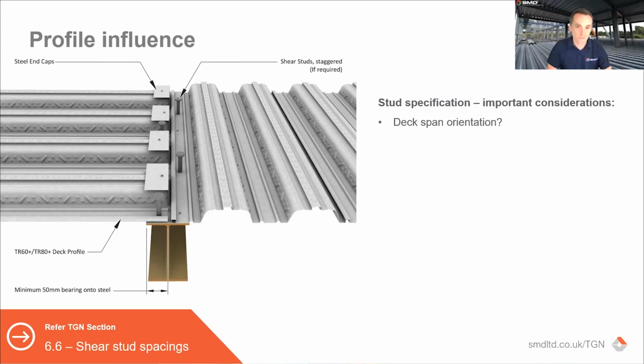So we've talked about the general spacings, and I just wanted to run through those on our products and what that means. There are a number of things that the profile influences in terms of what you can and can't achieve with shear studs and shear stud spacings on a beam. One is obviously the deck orientation. If you have a change in span, like we see here, with the deck running left to right on the left of the beam and into the page on the right of the beam, then you can only put studs at 333 centres for a TR60 plus on the left of that beam.